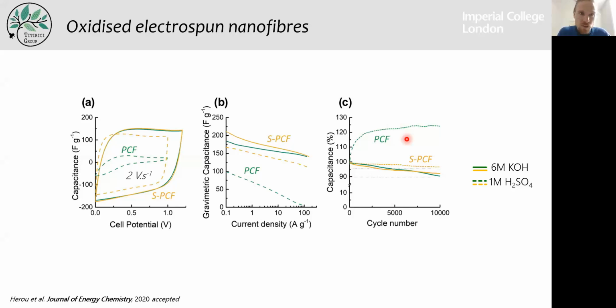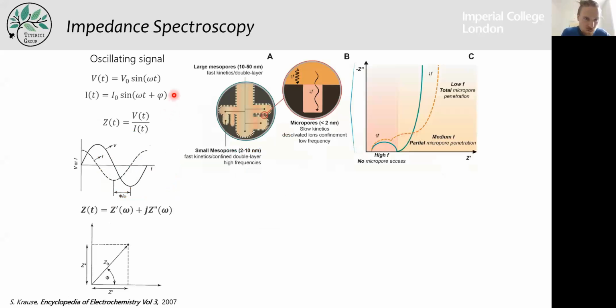So we decided to look a little bit more into this and perform some impedance spectroscopy. Just for some of you who are not really familiar with the technique, this is basically applying an oscillating signal on our device between the working and the counter electrode, and in this case we apply a potential. The potential is a sinusoidal curve, and then we observe the trend that the current has, and we measure the dephasing angle. And the impedance, which corresponds to the resistance of the device depending on the frequency, will be calculated by doing V over I. And as both of these values are complex values, we can write the impedance as equal to a real component and a complex component.